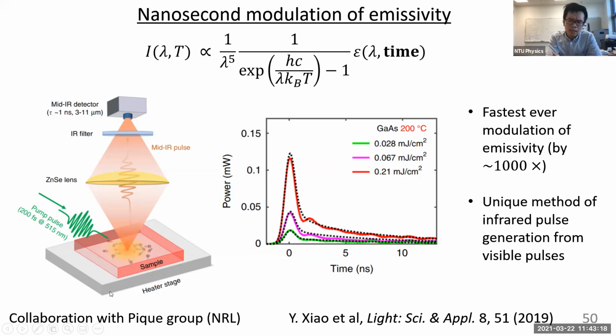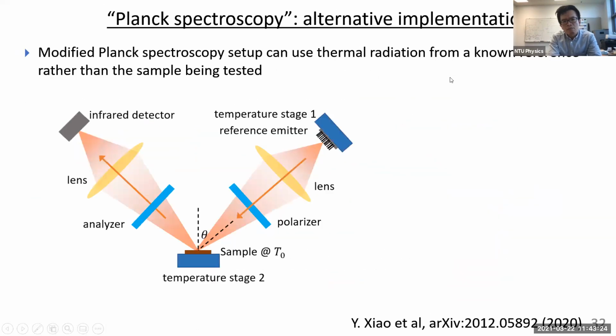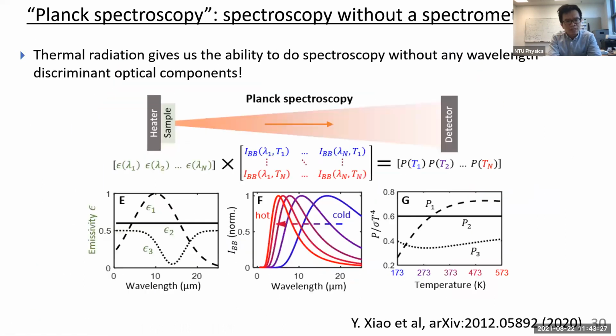So in terms of this Planckian spectroscopy, you're really doing just an inverse kind of problem, and that really depends on the fact, actually, this is a great slide, that these samples are emitting in a kind of normal Planckian way, multiplied by the emissivity, right? Yes, that's right. Sure. But what happens if you have a whole bunch of, say, phonon modes that are there? Does that screw things up? No, not at all. That's all accounted for in the emissivity. That's what you're looking for.